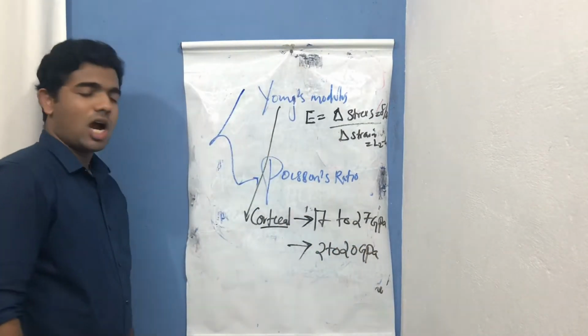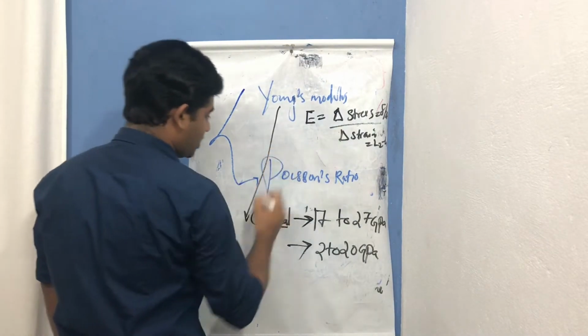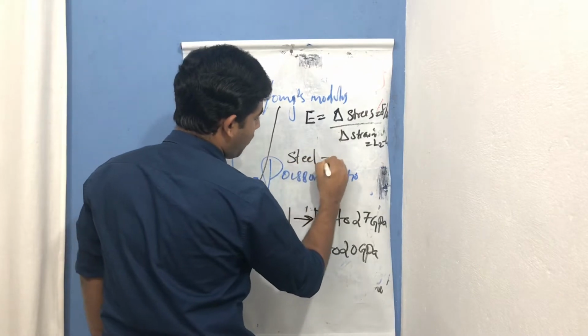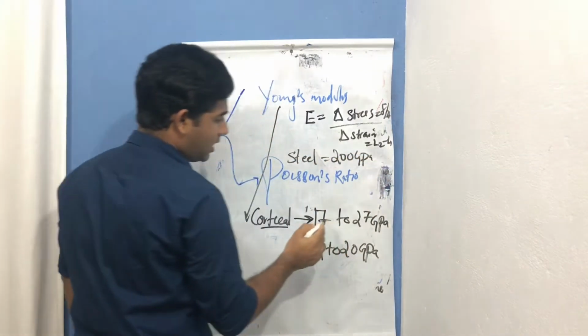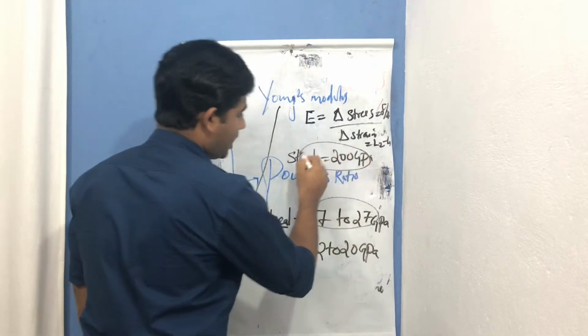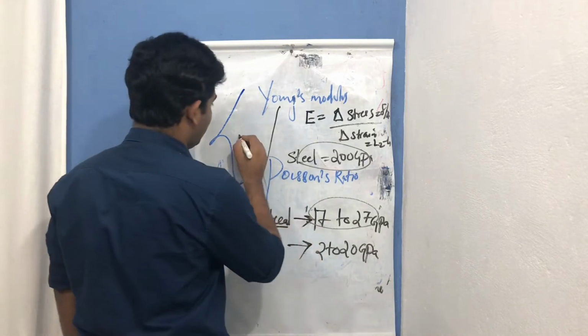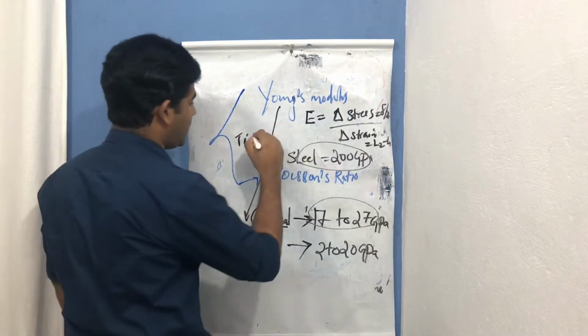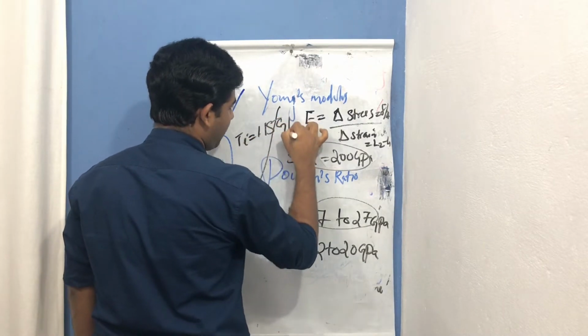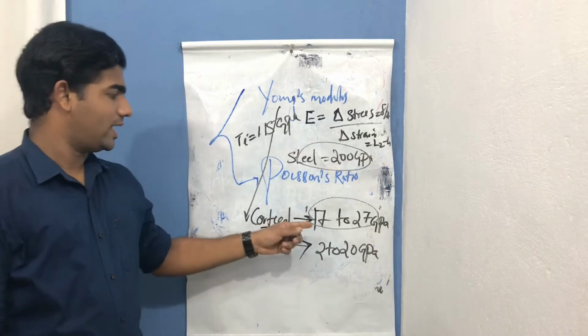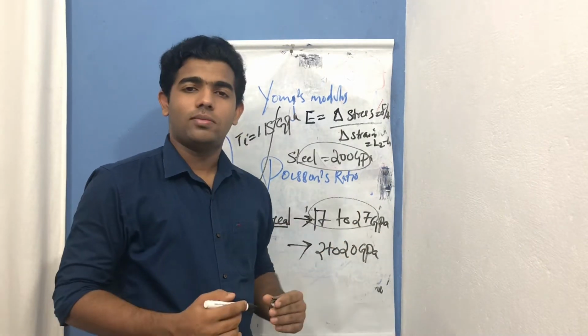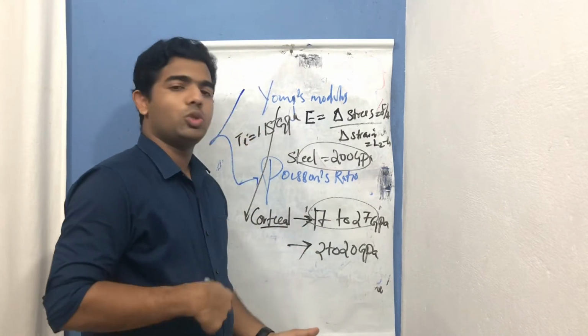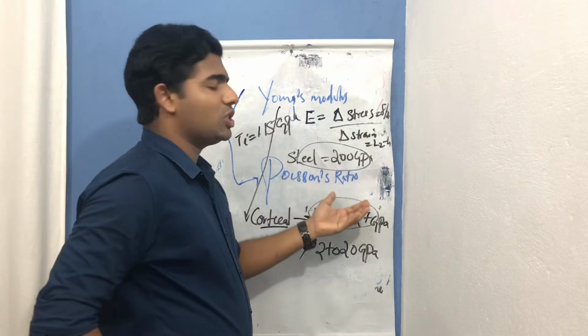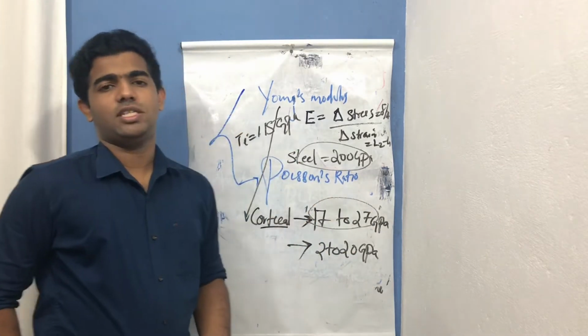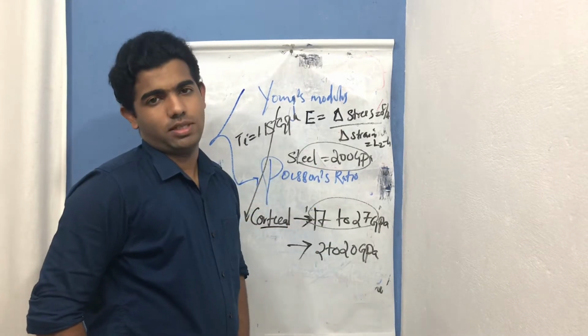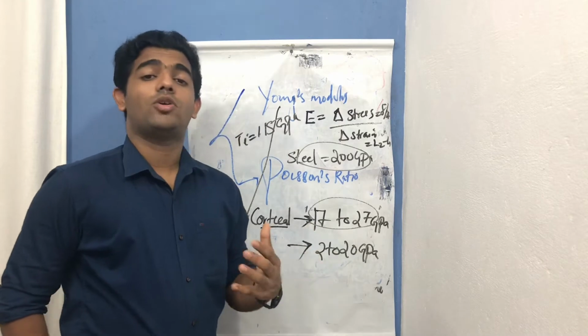2 to 20 GPa. How do you relate this to a real life scenario? For example, steel has a Young's modulus of 200 gigapascal. See the difference? The bone is having only 17 to 27. This is having 200. The titanium alloy that we use in our bone graft and in joint replacements has a Young's modulus of 115 GPa. See how much lesser the Young's modulus value of the bone is? The bone is 17 to 27 GPa, steel is 200 GPa, whereas titanium is 115 GPa. Right? There is a value difference between cortical and cancellous bone.